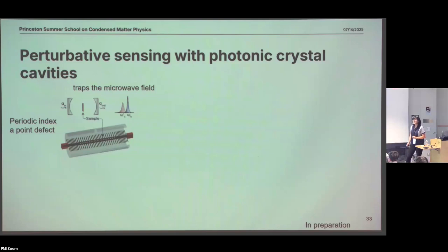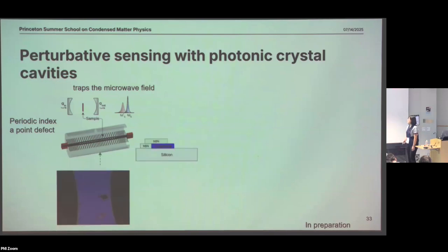So this drove us to do some instrumentation in the past year. Now, instead of having the tip capacitively coupling directly to the sample, we put the sample on a silicon photonic crystal. Here is how the silicon photonic crystal looks. It has a periodic modulation of the refractive index, and that makes forbidden transmission possible in a range of frequency. And those dots, as you can see here, are point defects. Those point defects can trap electric field effectively. So if you put a sample somewhere close to the center of this whole thing, you can have a huge enhancement of field. And that is one way of increasing the sensitivity.